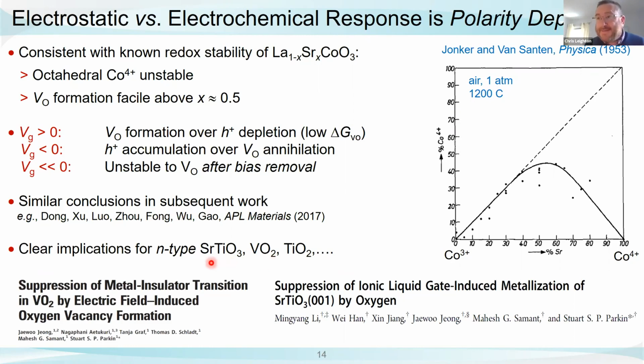Those are materials that are N-type. They can only be turned on in the positive bias direction because they only have significant mobility for electrons and not holes. And that means that they have to be operated in the direction where it's very likely that one can form an oxygen vacancy under the electric field, okay?